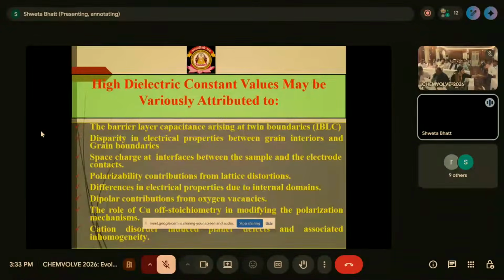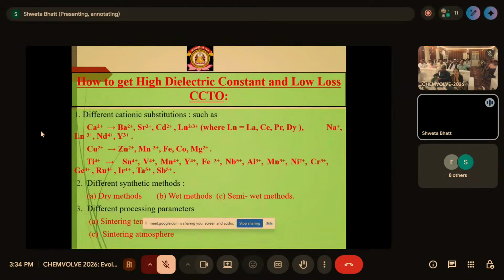There are a large number of reasons for the high dielectric material. One of the main reasons is the IBLC, the internal barrier layer capacitance between the semiconducting grains and insulating grain boundaries, because in CCTO there are different types of grains: some large grains, some small grains, and there may be an interface between them. The grain boundary is an insulating boundary, and it can cause the high dielectric constant of that material. We need a high dielectric constant for that purpose, so that provides a good material.